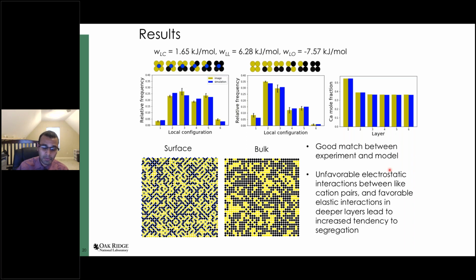So what we got out from this is that basically unfavorable electrostatic interactions between the lanthanum and lanthanum atoms, as well as favorable elastic interactions, basically tended towards increased segregation. And this is a result that was also quite similar to DFT simulations that were performed at MIT a few years ago. But this actually didn't use any DFT, right? So we just go straight from experiment to these kinds of interaction energies, and we can get the same kind of results that you would get from first principles on this particular system. Mind you that first principles are a little bit difficult for manganites, but nonetheless, it's a good proof of concept that you can use this method to be able to predict for relatively complex systems like manganites.